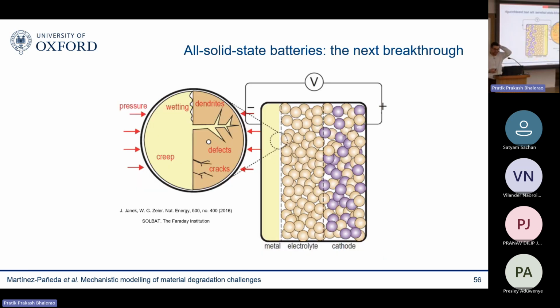And then finally, the last item I want to discuss with batteries is what we call all solid-state batteries, which are supposed to be the next big breakthrough in battery technology. And the idea is that by replacing a liquid electrolyte, not only do you gain in safety, since you replace something that is flammable by a solid electrolyte, but you can also use lithium metal as the anode, and that will give you an order of magnitude higher capacity.